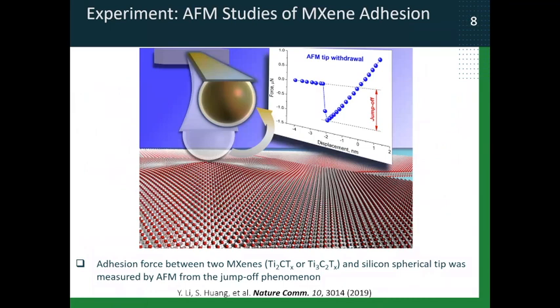related to modeling. Now we are going to switch to experiments with MXenes. We also do a lot of experimental science with MXenes related to mechanical properties, to tribology. And here's one example where we measured adhesion between MXenes and other materials. So in this experiment that is shown here, we used AFM tip. It's silicon tip with a native layer of silica oxide on it. And we measured force required to detach this tip from MXene monolayer deposited on the substrate.